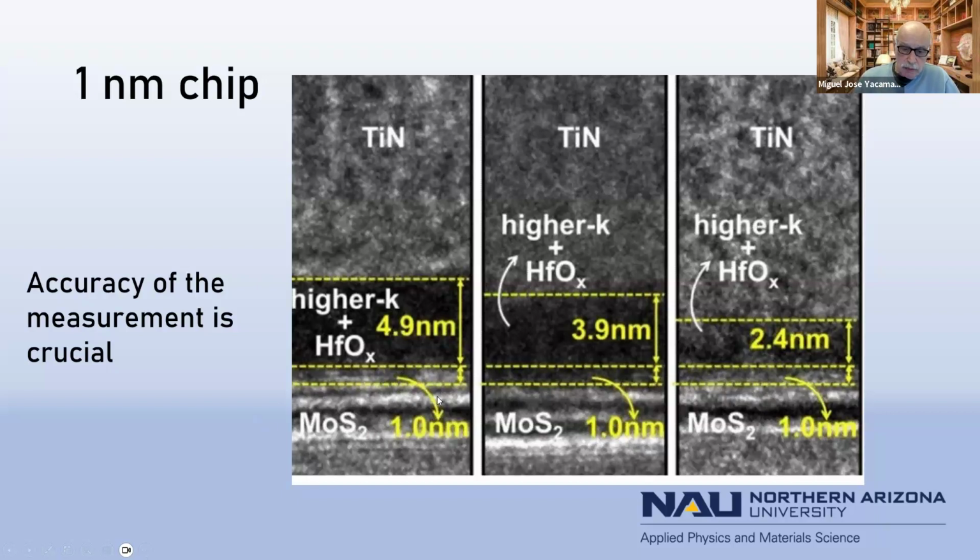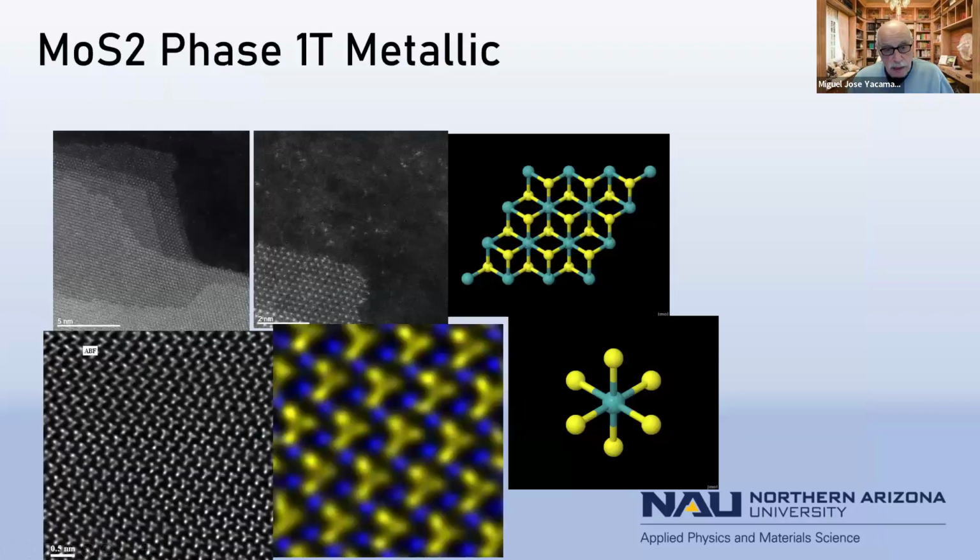In the case of molybdenum disulfide, it's a very peculiar material because it comes in layers. To use it in the electrodes, you have to delayer it and produce individual layers of 1 or 3 layers. This material is like a sandwich in which the bread is sulfur and the ham is molybdenum, and it comes in layers. It's so delicate that the number of layers determines whether it's a semiconductor or a metal.